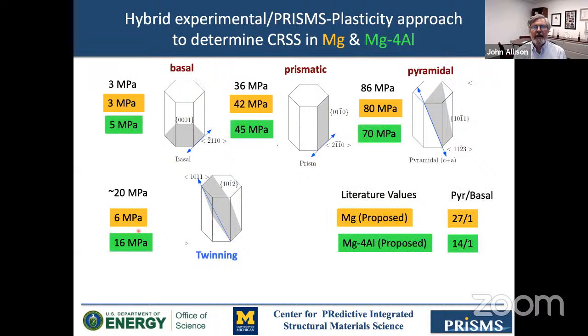So then we've also done the same thing in Mg-4Al. As we might expect, solute hardening increased basal slip. It increased prismatic slip a little bit. Actually, it decreased pyramidal slip, but it also substantially increased twinning. So this is a really, we think, important finding that alloying actually does increase, at least for aluminum, the twinning resolved shear stress. Also, we see that it decreases the pyramidal to basal ratio. And this is very important for understanding texture and plastic anisotropy. And I'll talk a bit more about that in a little bit.